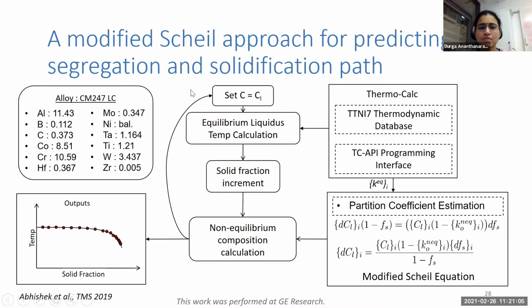So the first approximation that we did was this modified Scheil approach, wherein we capture the non-equilibrium effects. So it's similar to Scheil solidification, but just when we calculate the composition of the solid and liquid at each step, we also include the effect of the non-equilibrium partition coefficient. And one more assumption that we do is the fraction of solid of the different phases that are formed. We assume that it's the same as equilibrium, which is not entirely correct, but that's the first approximation that we used.